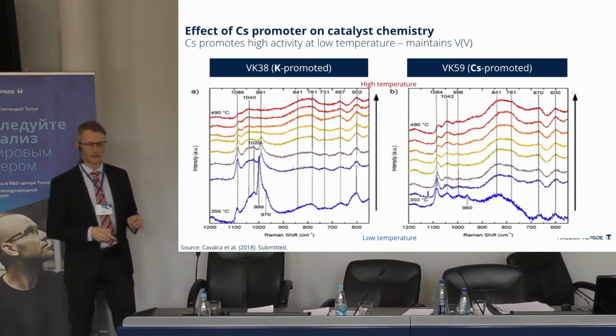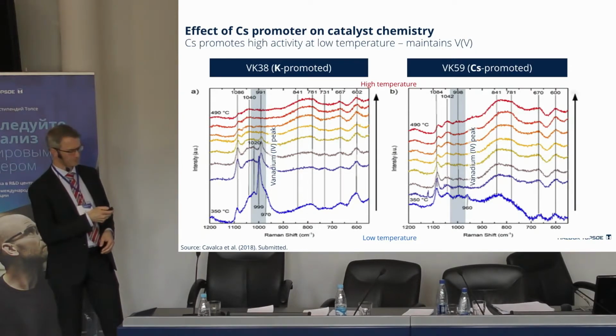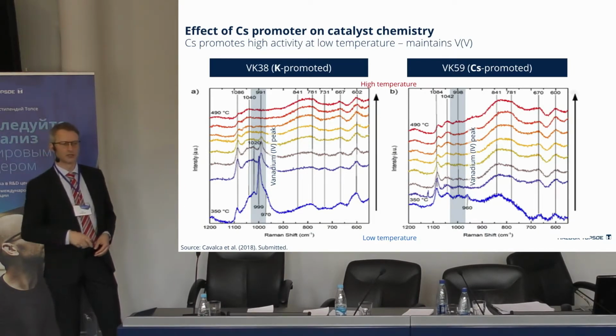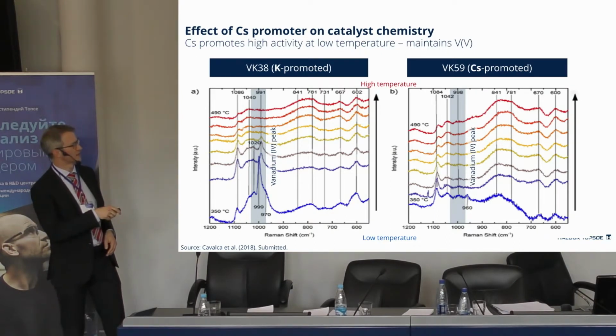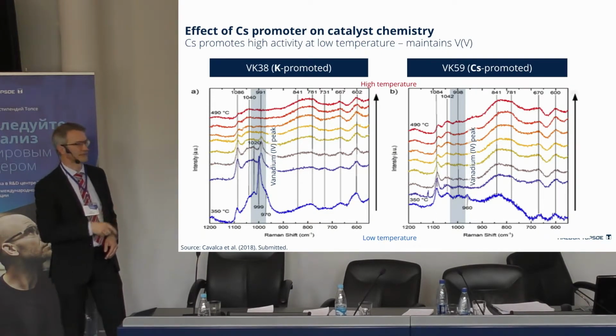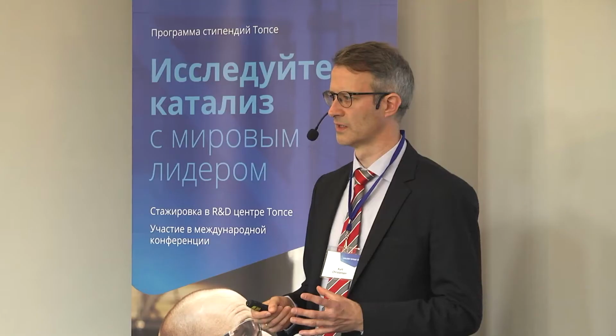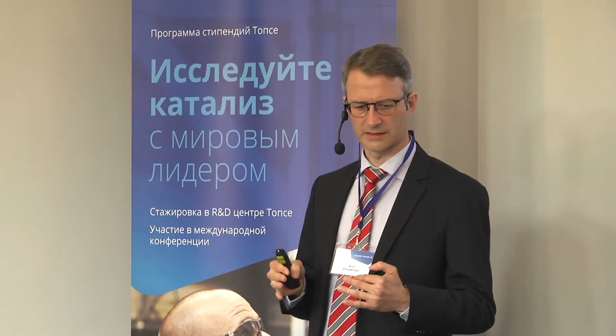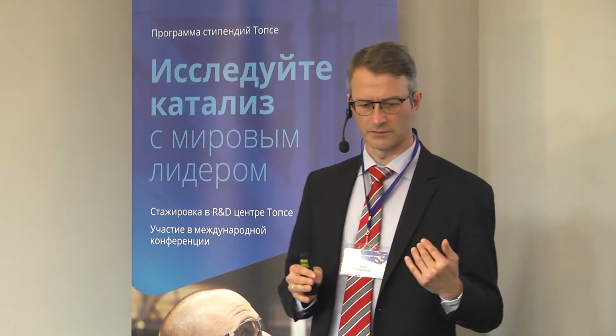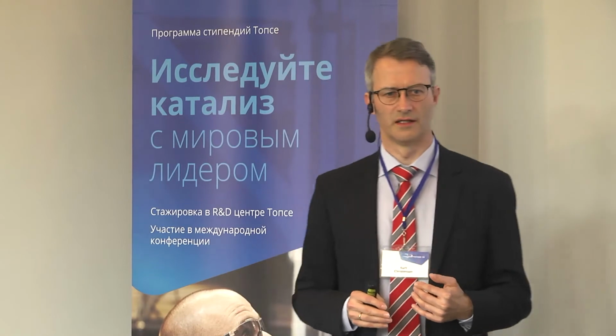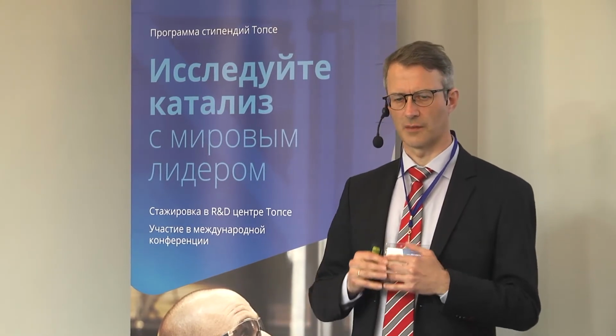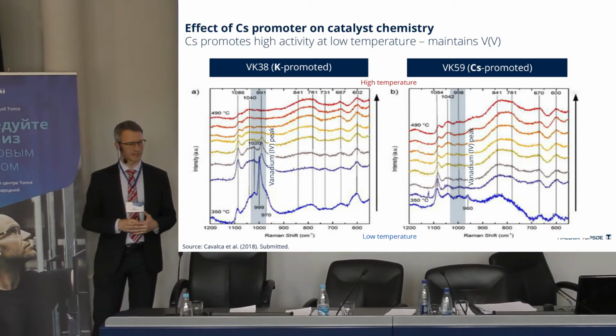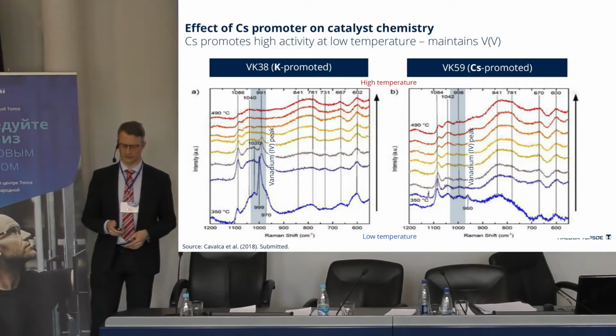If we zoom in on the peaks related to vanadium 4, we see some very distinct peaks in the VK38, especially at the lower temperatures, where we see the vanadium 4 compounds. However, they are almost not present in the VK59, which is cesium promoted. So we find in these studies that the cesium stabilizes linked vanadium 5 compounds, and in this way it maintains vanadium in state 5 instead of reducing to oxidation state 4.